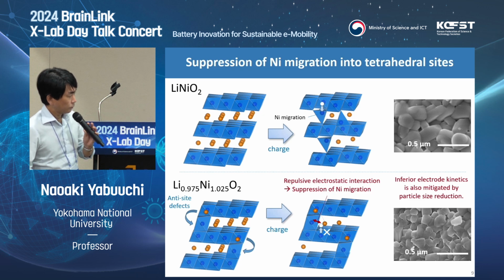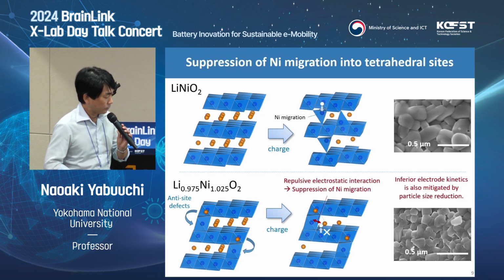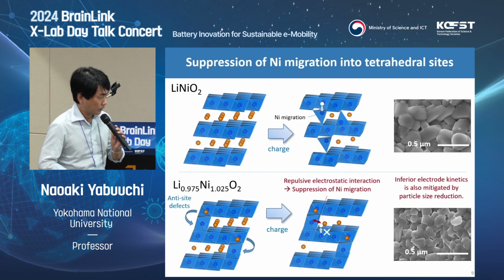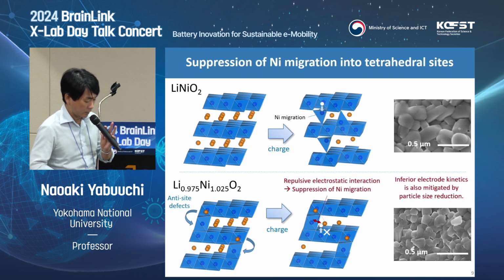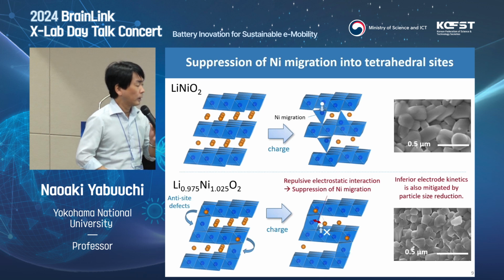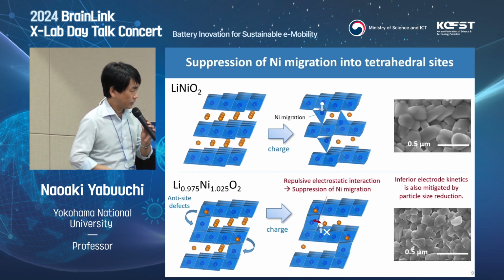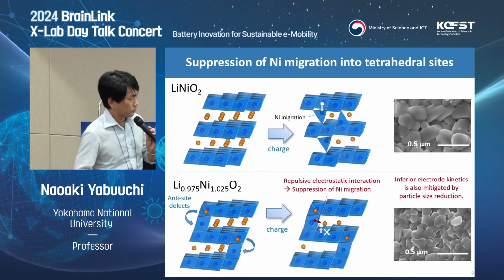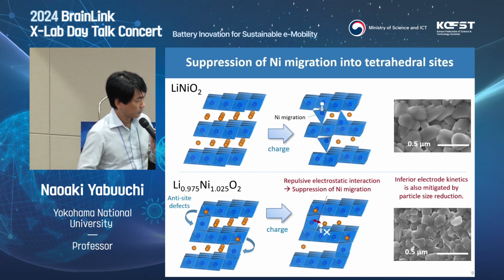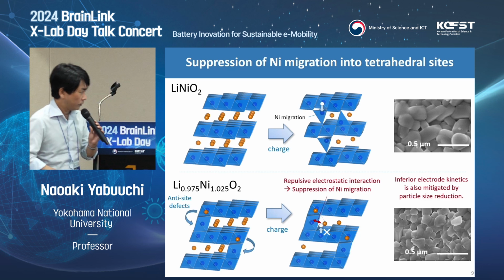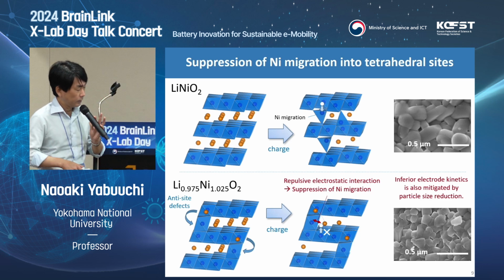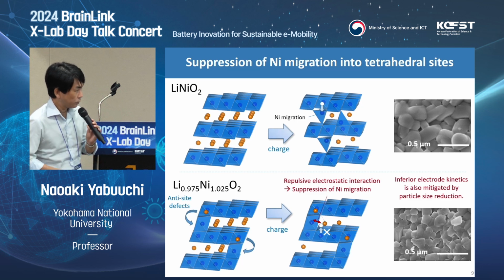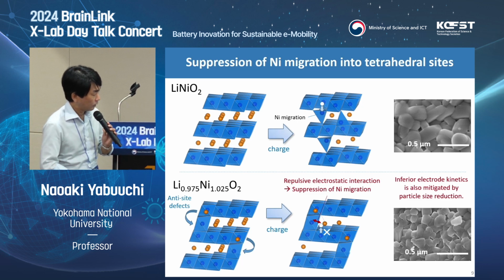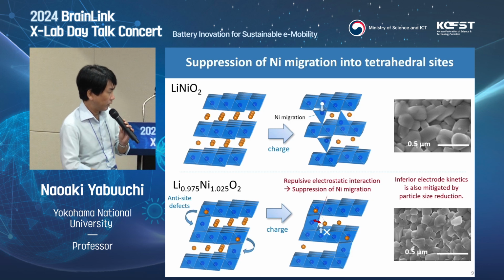However, for the anti-site defect samples, we have a small amount of nickel ions in the lithium layer. Therefore, even after lithium removal, nickel ions cannot migrate to neighboring tetrahedral sites because of repulsive electrostatic interactions. You may also notice that the presence of anti-site defects disturbs lithium ion migration. However, particle size is clearly smaller compared with the stoichiometric samples. Therefore, increased surface area with a small amount of anti-site defects, coupled with a very chemically stable, highly concentrated electrolyte solution, we can improve reversibility for pure lithium nickel oxide without cobalt ions.